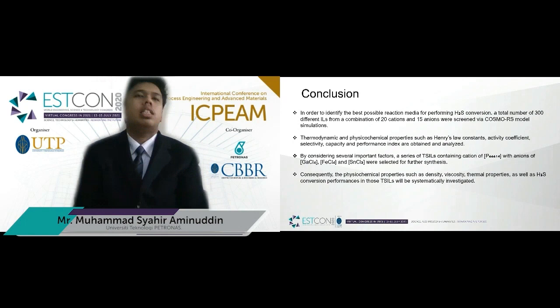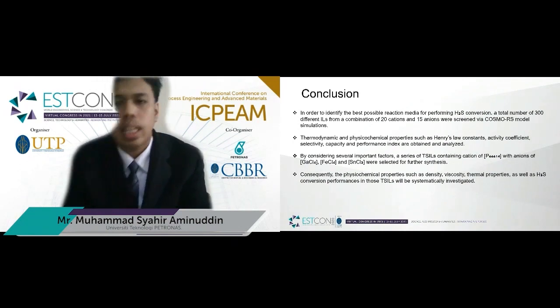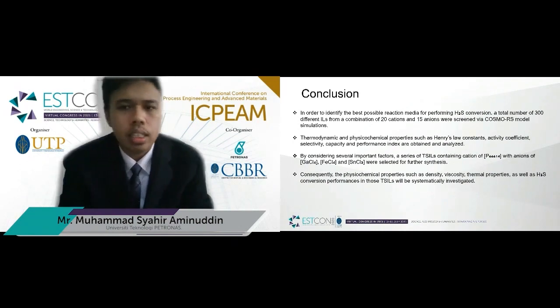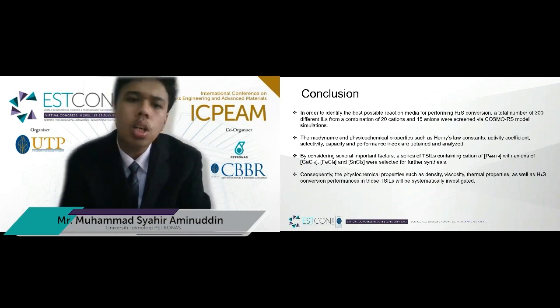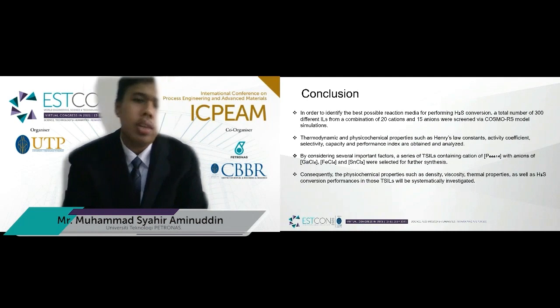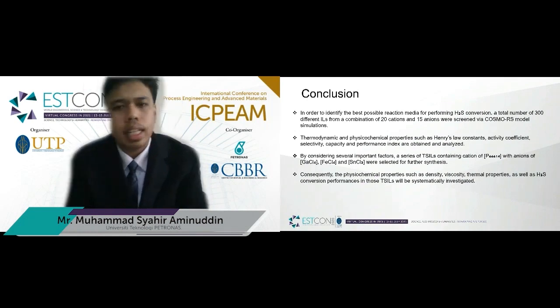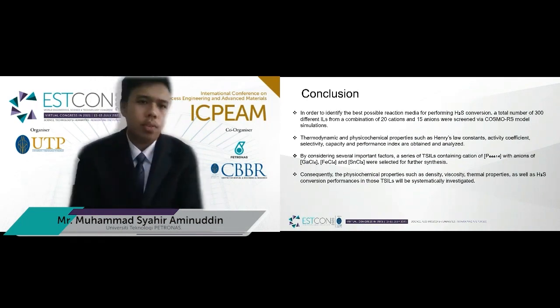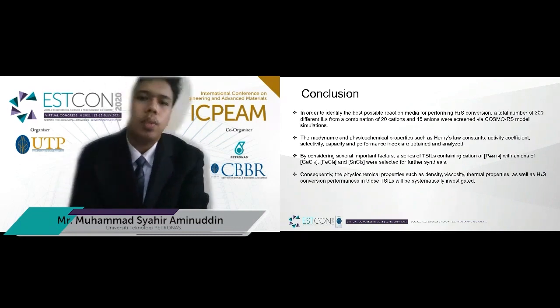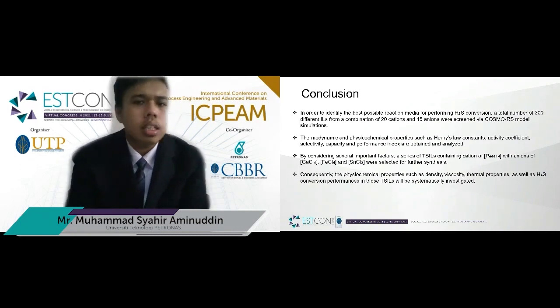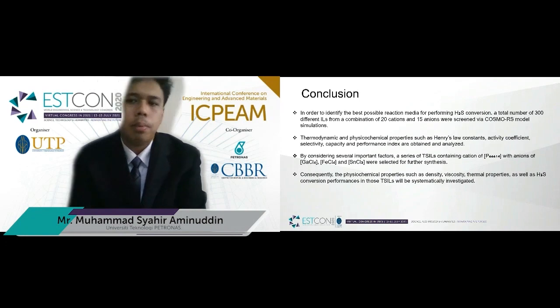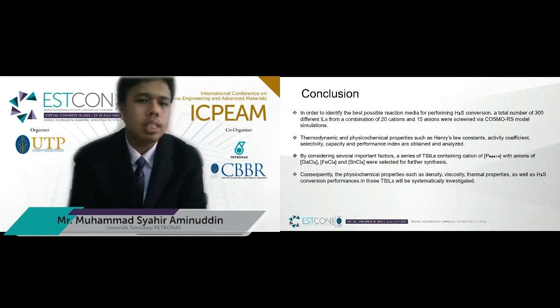By considering several important factors, a series of ILs containing cation of trihexyl tetradecyl phosphonium P66614 with anions of tetrachlorogallate, GaCl4, tetrachloroferrate, FeCl4, and trichlorostannate, SnCl3, was selected for synthesis. Consequently, the physicochemical properties such as density, viscosity, thermal properties, as well as conversion performances of these ILs will be systematically investigated.